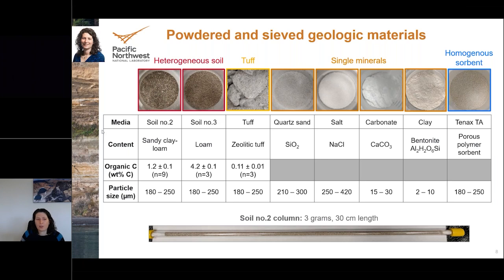And then because the soil and geologic materials are inherently heterogeneous, we also evaluated a homogeneous sorbent called Tenax TA. This is a porous polymer sorbent. And we did this to help assess the variability in our measurements versus just the variability that's innate to other materials. The geologic materials have a range of organic carbon contents, which I've shown down here. So in this case, ranging at most, we had about 4% down to just a little bit over 0.1%. And this can further add to that variability in results or heterogeneity.